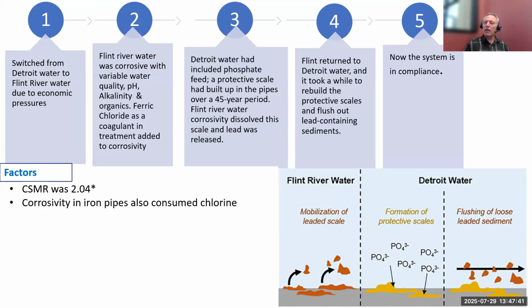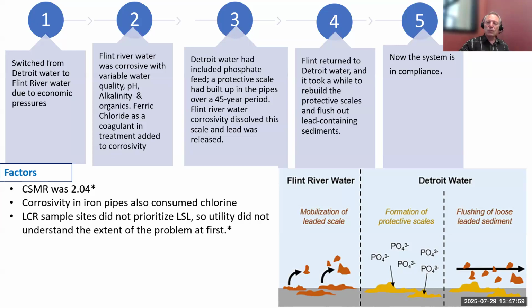Another problem is that as corrosivity went through the system, iron pipes, especially cast iron pipes, also were corroding, and that ended up consuming chlorine. So you had two things going on. Not only did you have the release of lead scales, but you also had the threat of reduced microbial control as chlorine was consumed. Massive chlorine demand from the iron pipes.